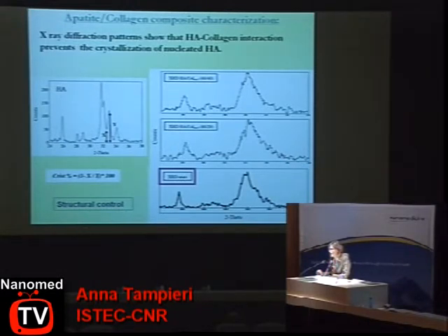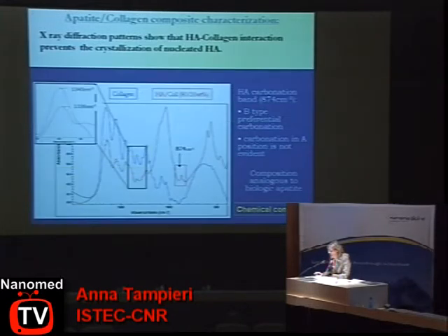Actually, the collagen prevents the crystallization of hydroxyapatite, so it is able to control the crystallization degree of the inorganic phase. Similarly, by infrared analysis, we can see that there is a spontaneous incorporation of carbonate ion instead of phosphate in B position, which is typical of newly formed bone. So we have also chemical control.